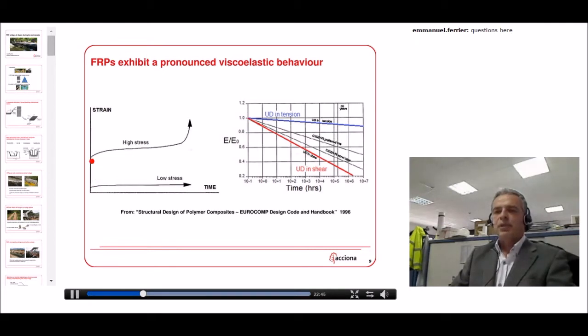If you load, for example, an FRP element and you keep the load constant, you have an instantaneous deformation. Then, with time, you develop a secondary creep. And then, if the stress is very high, you have a tertiary creep, or you get a creep failure. So the first step in designing an FRP girder is to limit the stress induced by sustained load in order to avoid creep failure.